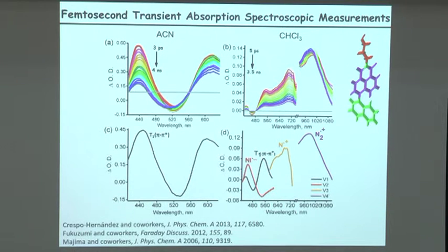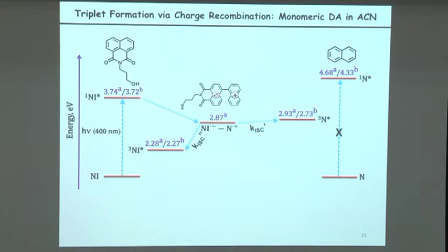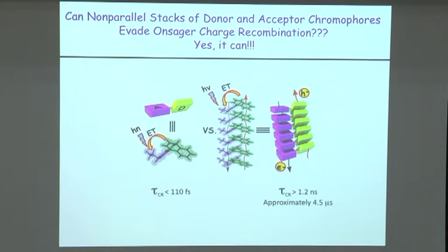One corresponding to naphthalenimide radical anion, which accepts an electron, naphthalene radical cation after donation of an electron from naphthalene, and then you get a dimer radical cation, which also says that the hole is getting delocalized across the naphthalenes. It's a nice work done by Kochi and co-workers in the late 80s and early 90s, that this particular species is characterized thoroughly. So we took that literature, and we can see that now the charges are hopping across the stacks that we are creating. So this is the Jablonski diagram.